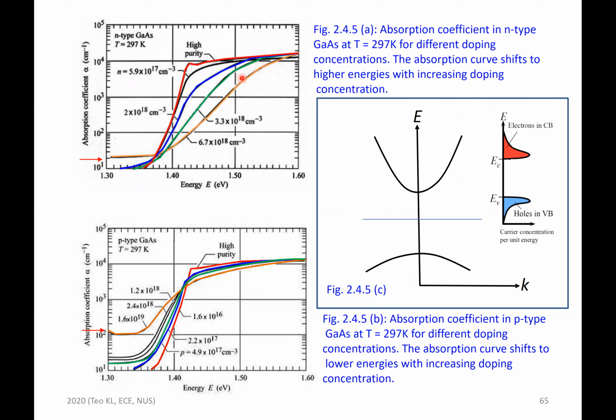Now, I thought I will explain again the absorption coefficient as a function of energy for n-type gallium arsenide. Basically, the gallium arsenide is doped with n-type shallow impurity and measured at 297 K, which is room temperature. So the red curve is the high purity gallium arsenide without doping. And then the blue, green, and orange are in increasing order of the carrier concentration.